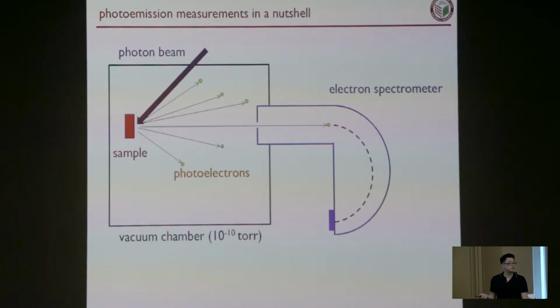Photoemission is a very surface sensitive technique. In this room, we'll have lots of molecules adsorbed onto surfaces. If that were happening here, the photoelectrons as they come out would get scattered, and you'd lose that energy and momentum information. So you want an atomically clean surface, and to keep one over many hours or a day of measurement, you need this kind of vacuum. The ballistic mean free path of an electron here is also much larger than it needs to be; you also don't want to be in air.